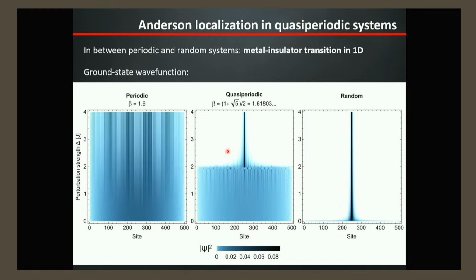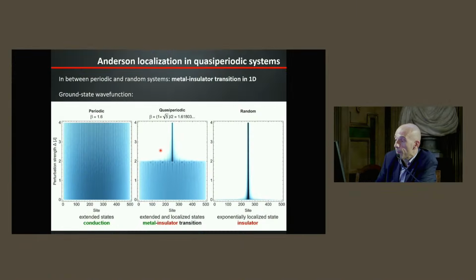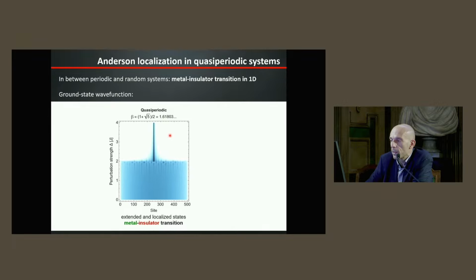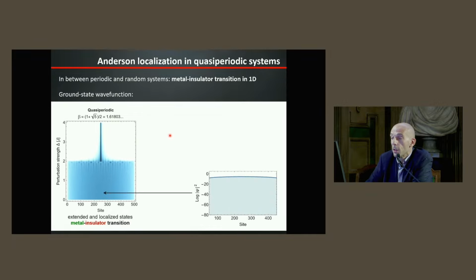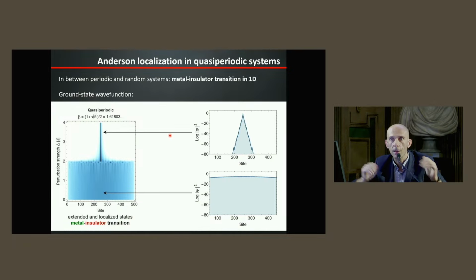But here you see that the quasi-periodic system exhibits a phase transition, a quantum phase transition, from a behavior at low perturbation strength that is very different from the behavior at high perturbation strength. If delta is sufficiently small, you have a metallic behavior, so your quantum particles will be spread out, delocalized across the whole lattice. If delta is too large, larger than some critical value, you get localization, exponential behavior. So this is interesting - you have in a one-dimensional system a quantum phase transition between two strikingly different regimes.